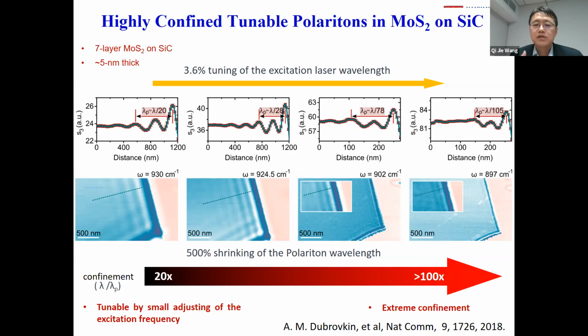Using the same system under the same operation condition, we had a very difficult time to measure graphene plasmonics, with the same confinement factor because of the relatively high loss. So here, indeed, this Phonon-Polariton system has a relatively low loss, which allow us to do some comprehensive investigation. So here we can achieve the Phonon-Polariton wavelengths 100 times smaller than the wavelengths of light in free space. And in the extreme measurement, we can achieve the confinement factor up to 105.